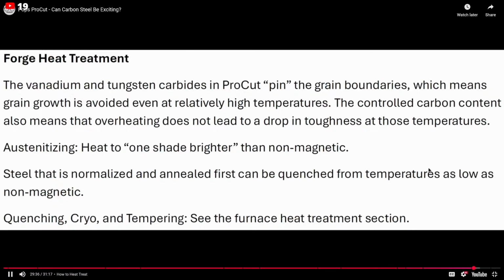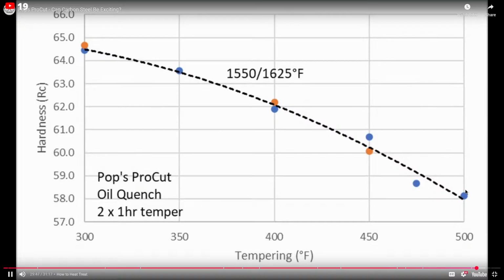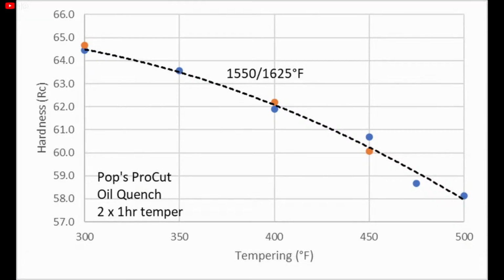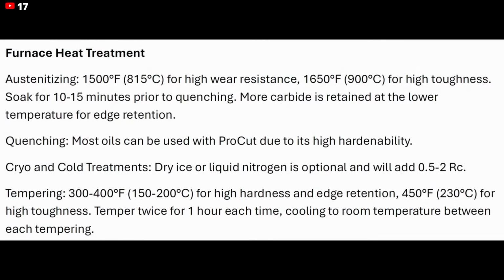If you're heat treating in a forge, you heat to 1 shade brighter after reaching non-magnetic, and you quench in oil. Most any oil will do. Then you temper twice for 1 hour each time at 300 to 450 degrees Fahrenheit to your desired hardness. You can do that in a regular oven. To maximize toughness, you use 1650 for 10 to 15 minutes. For higher edge retention, you use 1500 for 10 to 15 minutes. Then you quench in oil and temper twice at 300 to 450 degrees.